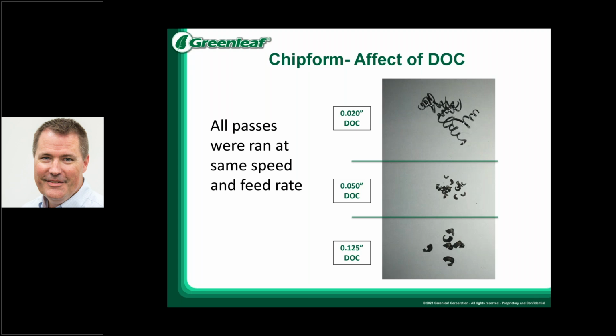On this slide, we show the difference between running the same chip form at the same exact parameters, just varying our depth of cut. By not pushing the insert into the correct depth of cut as recommended, you'll see where the chip form dramatically changes. The top image with the 20 thousandths depth of cut, you can see the chips are much longer, stringier, and can end up creating a mess within the operation, possibly even allowing those chips to get tangled around the workpiece, around the tooling, which can cause damage to the tool itself or shorten your tool life.